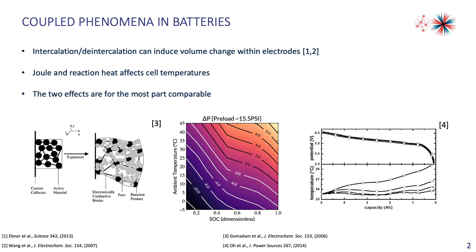In this experiment, where prismatic cells were held in compression against load sensors, we measured the force response from either an SOC or temperature stimulus. Depending on where you stand on this contour plot, either one of these effects can become the major contributor to the stress evolution. For example,